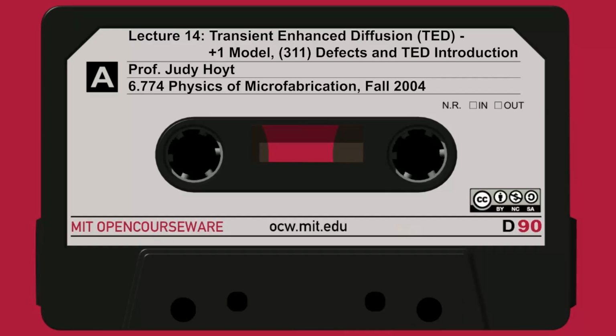And now I'm going to solve for the concentration of interstitials, because the cluster concentration drops out, right? So I can solve for the maximum interstitial concentration just in terms of the ratio of k_F and k_R. Going back to slide 15, I can then figure out a maximum concentration of interstitials that are trapped in these 311s. It's just k_R over k_F, and it looks like this. It depends exponentially on the binding energy over kT. So that is an estimate of the maximum number of excess interstitials. If I divide that by C_I star, that gives me the supersaturation ratio.